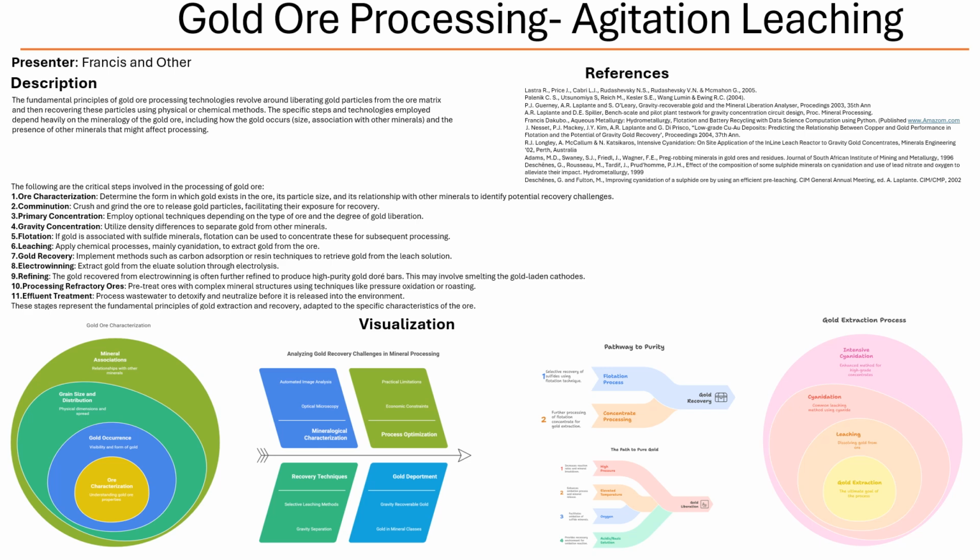And that results in much higher gold recoveries, right? It does. We're talking 95 to 99% recovery. Wow, that's impressive. So why isn't tabling used as much anymore? Well, tabling has a number of limitations. For one thing, it's very labor intensive. You need skilled operators to run those tables, and it's also not as efficient as intensive cyanidation, especially when dealing with very fine gold particles.